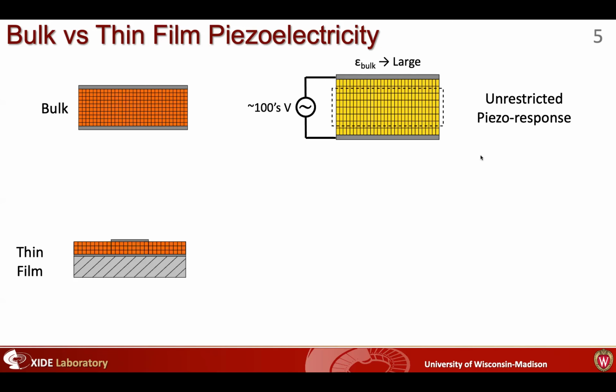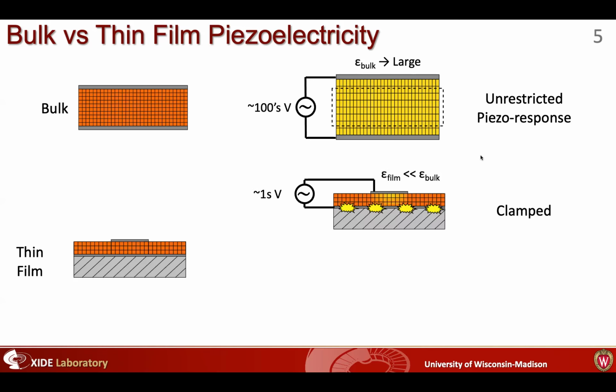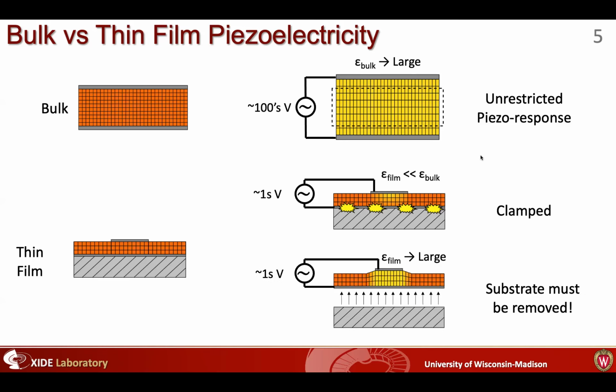To reduce that voltage and make it more applicable for memory devices, you really want to work with thin films. Lane Martin also highlighted that with a thin film, even though you now only need maybe single digits of volts to switch the polarization, your strain generation is very much reduced due to this substrate clamping effect. So my entire project at Wisconsin involved removing these films completely from their substrate and recovering that giant piezoelectricity.